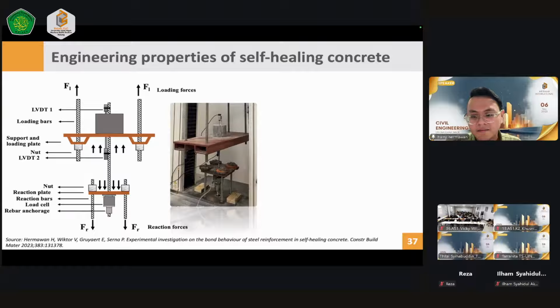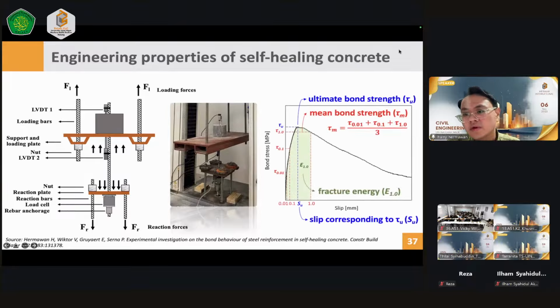And from this setup, we will get a lot of information. For instance, we can evaluate the ultimate bond strength, which is very important. We can also determine the mean bond strength, fracture energy, or calculate the slip corresponding to the ultimate bond strength. But I cannot explain a lot of concepts here, so we just focus on one parameter, which is the ultimate bond strength.